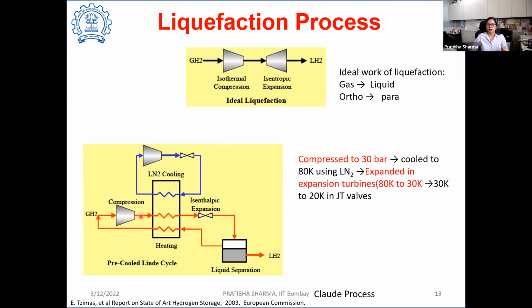It has to be compressed to a higher pressure, that is 30 bar. Then it has to be cooled down in a liquid nitrogen heat exchanger to bring its temperature down to 80 K. Then it has to undergo an expansion in an expansion turbine where its temperature goes below 30 K. And finally, a Joule-Thomson valve is used to lower its temperature down to 20 K. Now the two most energy intensive steps in the process are the compression to 30 bar and the expansion in an expansion turbine. These eat up most of the energy.